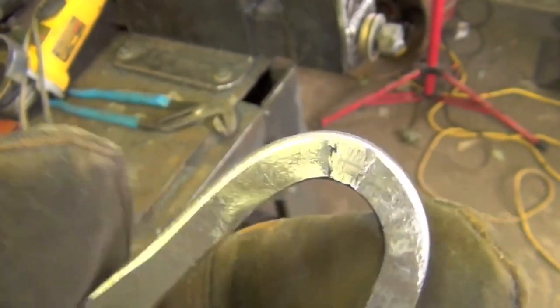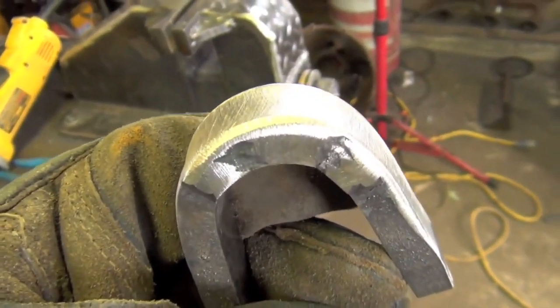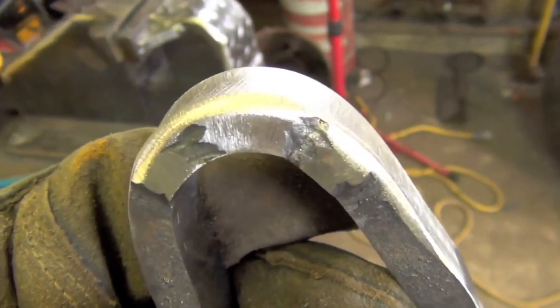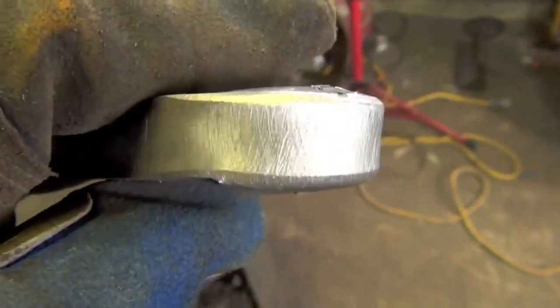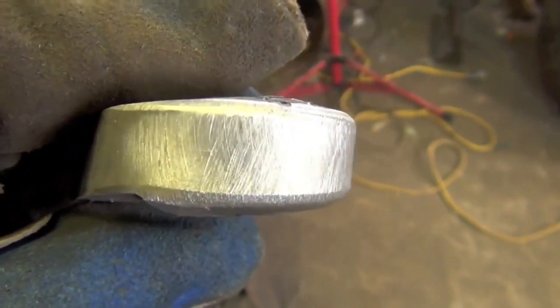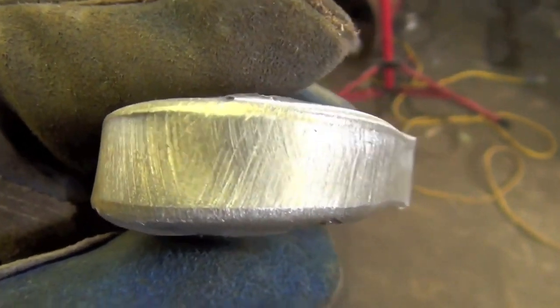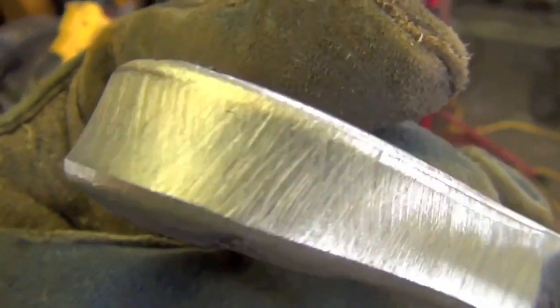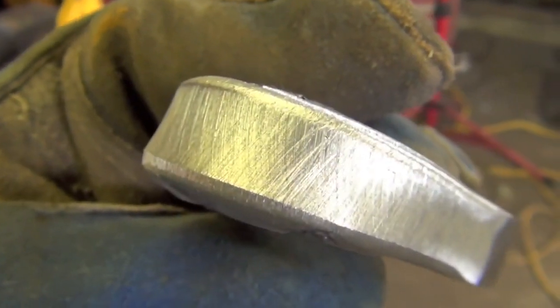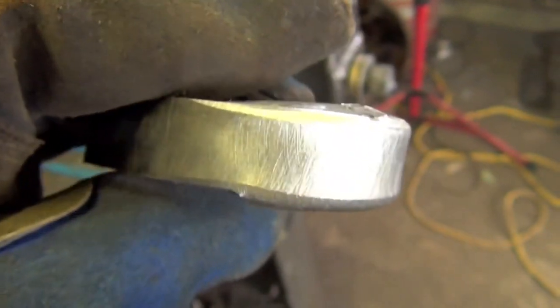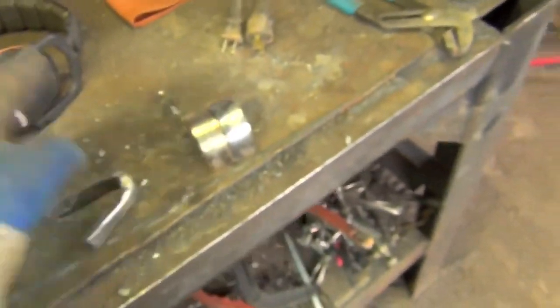But as you can see, there's the root. Yeah, look at it this way. It looks a little bit better. And here's the face. You can see where they were because I obviously didn't completely grind them flush. And this is the part that I did grind flush. And when you look at it, all you see is the grinder marks. There's nothing popping through. There's no cracks, defects, or trapped slag. Nothing along those lines. It's just pure weld metal. So I guess we can call this test a success.